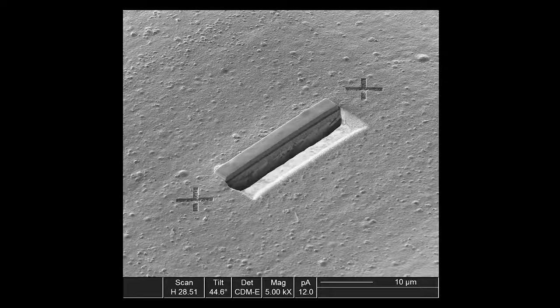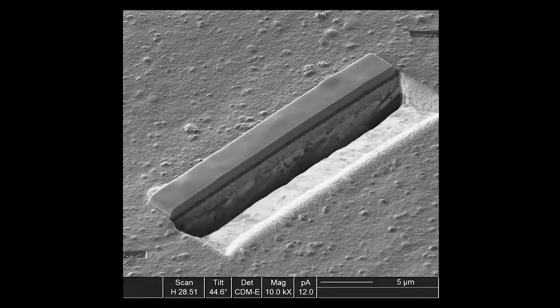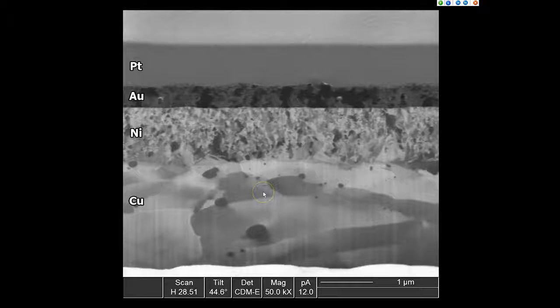So when we tilt this and look at it from sideways, now you can see there's several layers in there beneath the platinum strip that we deposited on the surface of the sample. And so we're going to examine this in greater detail. So what we have here is the substrate is a copper plating in this case, and on top of that there's a nickel deposit, and you can tell based on the grain structure that it's an electrolytic nickel in this case as opposed to an electroless type nickel, and that's perfect for this application.